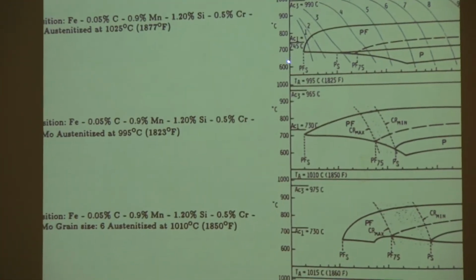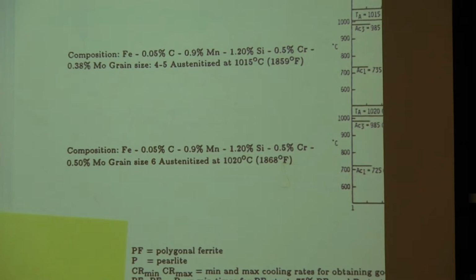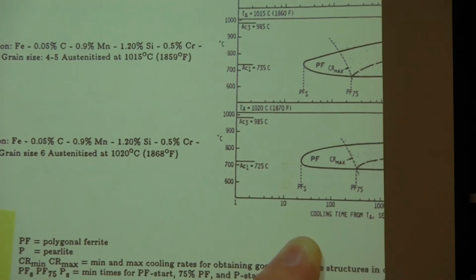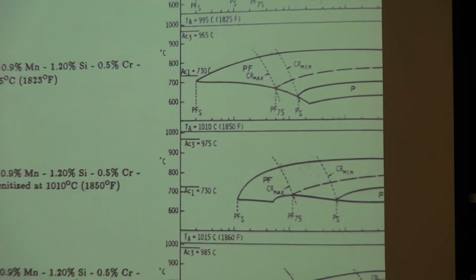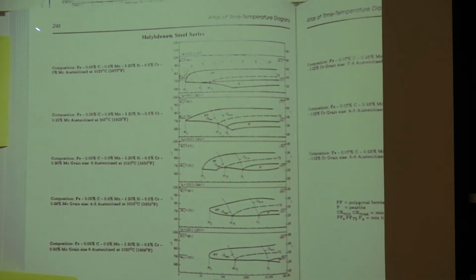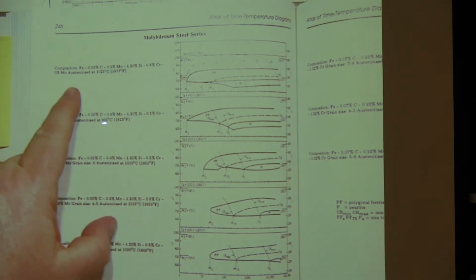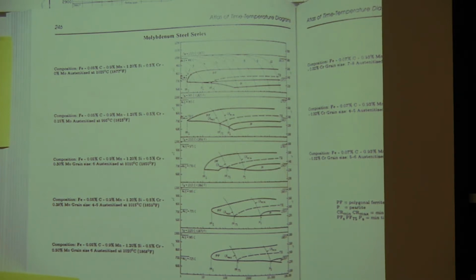This is a molybdenum-free steel, and I have to transform it. You can't see the plot down here. It's probably on the very bottom here. It's 1 second, 10 seconds, 100 seconds. This is just a series of steels with 0 molybdenum. This is 0.15 molybdenum, 0.3, 0.38, and 0.5% molybdenum. And you can see how molybdenum is changing the nose of that C-curve over from a second to 20 seconds. Okay? I can slow the reaction down by a factor of 20 by adding 0.5% molybdenum to the steel. Well, that does cost me a little bit.